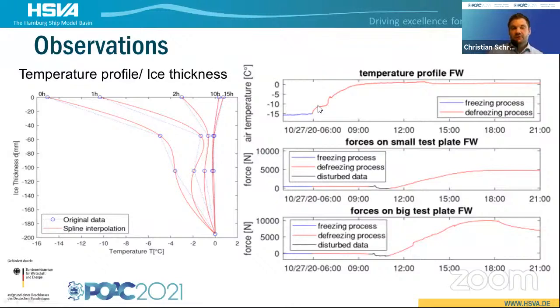If we now switch here to the right-hand side to the corresponding temperature load profiles, you can see on the upper figure the temperature profile of the room. So it was about -15 degrees in the morning. We started the tempering process. So the temperature itself got up to about 0 degrees after something like 3 hours for the freshwater part now.